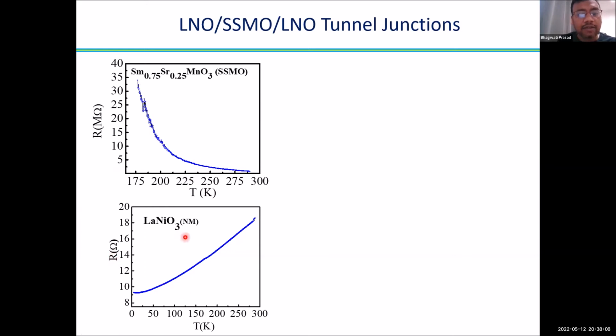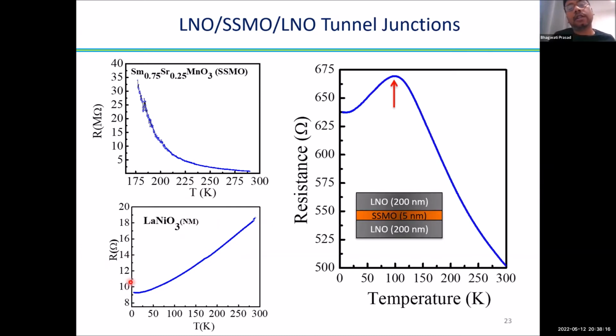And this is the R versus T of lanthanum nickelate, which we use as the electrode, showing the metallic behavior. Now when you measure the R versus T of a device which has 5 nanometers of SSMO sandwiched between the two lanthanum nickelate electrodes, this R versus T data is different from these two.